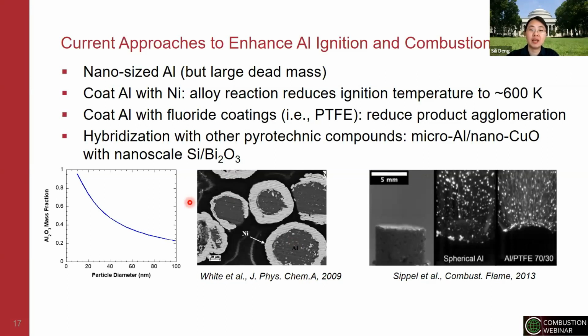However, the nano size not only would be quite expensive to manufacture, but also, because aluminum is relatively active and reactive, all the natural aluminum would have a natural oxide layer coated at the surface. So if you think about this, when the size shrinks to nano size, we know that nanomaterials have a relatively larger surface to volume ratio compared to the bigger size. So you can imagine there is a larger percentage of aluminum oxide at the surface in the nano-sized aluminum particles compared to the micro-sized counterparts.